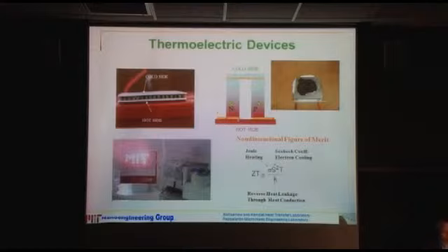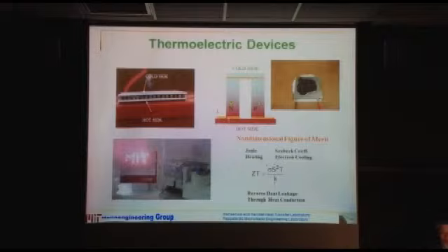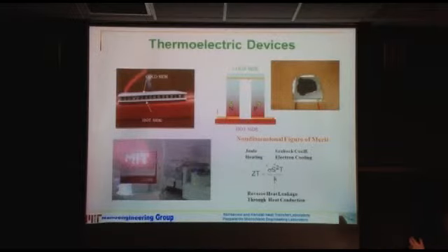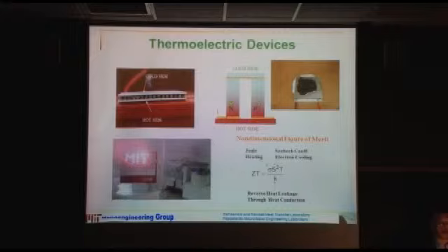And we want this also so-called Seebeck coefficient. That's when you use a thermocouple, per degree temperature difference, how much voltage you measure. And then we have in the denominator this thermal conductivity, and we want it to be low because if you think about making a refrigerator, this side is cold, this side is hot. In the household refrigerator, you put a thick thermal insulation to isolate the ambient from the cold compartment. And in our case, the material itself has to be that thermal insulation. So it has to be a good thermal insulator, a good electric conductor, and we want per degree temperature difference to generate a lot of voltage. So that's difficult, and this is where the material research has been very difficult.